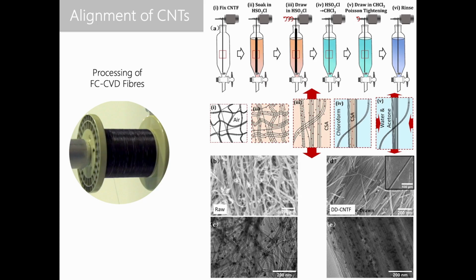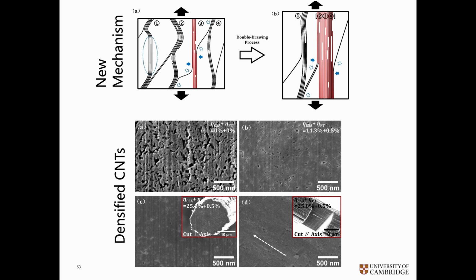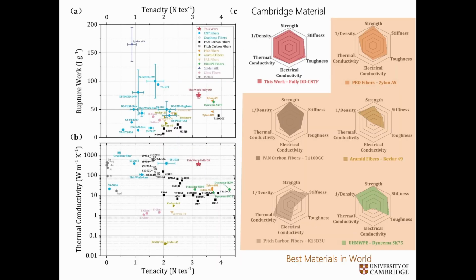So the way we, as a community, have been doing this, and this is work from our lab, is that you put these materials into very strong acids. Those acids give protons to the surface. Those protons repel the nanotubes and overcome the surface energy. And then if you can do that, then you can substantially align these materials. And that's how we go from fibers that initially look like this, to fibers that look like this and become very dense. And so that game is being played as well. It's kind of an outside of the reactor thing, but we're playing that game.